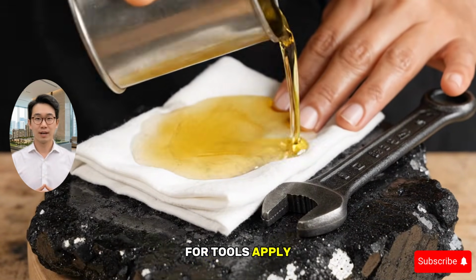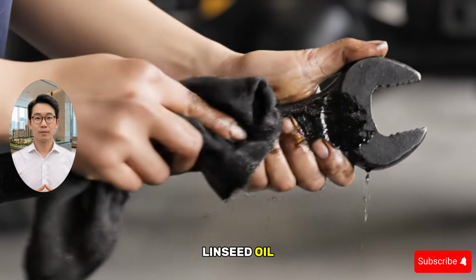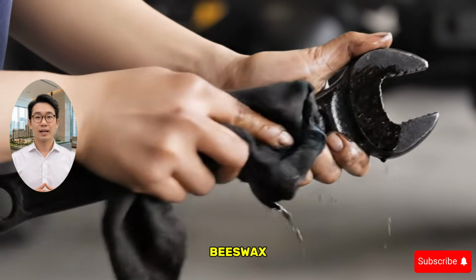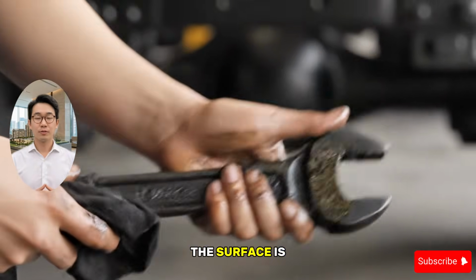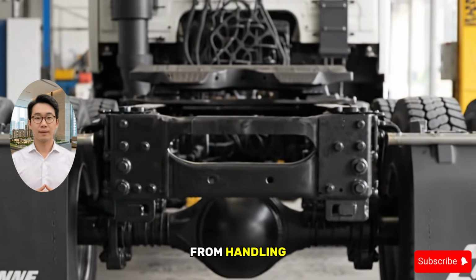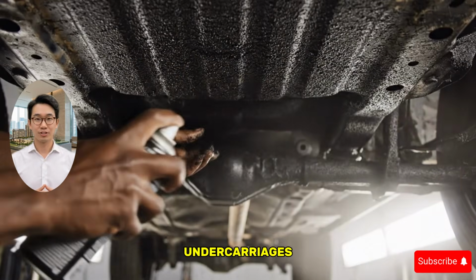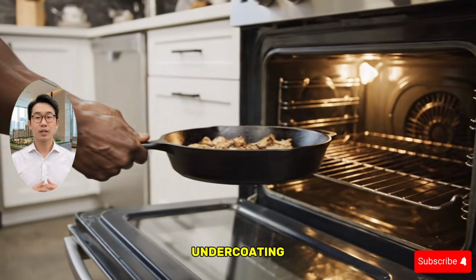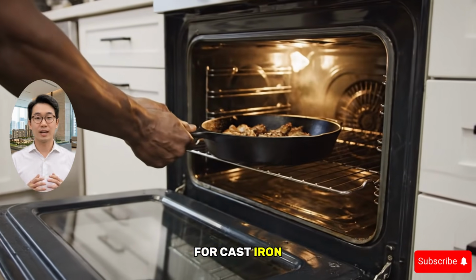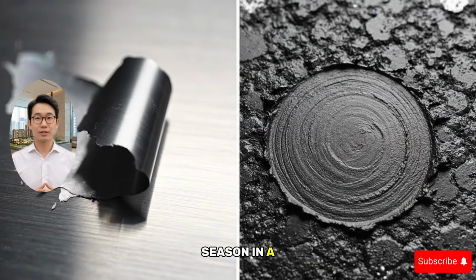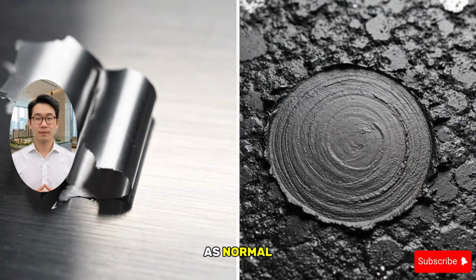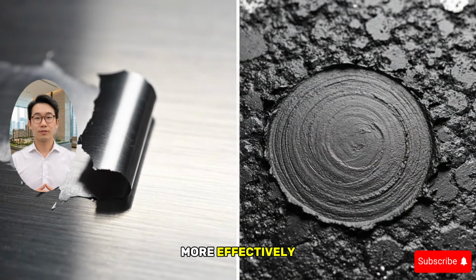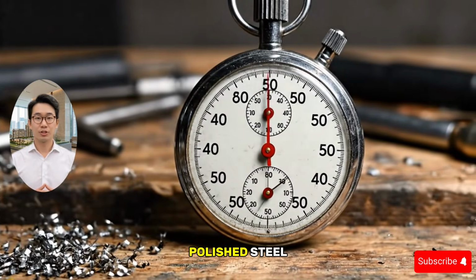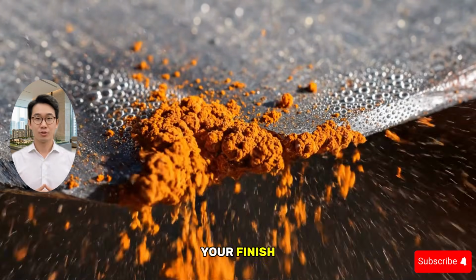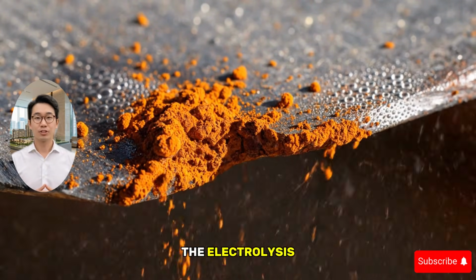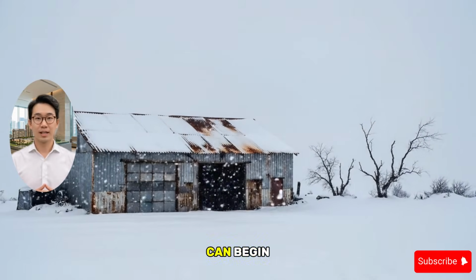For tools, apply a thin coat of boiled linseed oil, mineral oil, or melted beeswax rubbed on with a cloth, while the surface is still slightly warm from handling. For vehicle frames and undercarriages, apply rubberized spray, undercoating, or used motor oil. For cast iron cookware, simply reseason in a 350-degree oven as normal. The magnetite surface bonds more effectively to any top coat than bare polished steel does. Apply your finish within 30 minutes of completing the electrolysis treatment before any surface oxidation can begin.